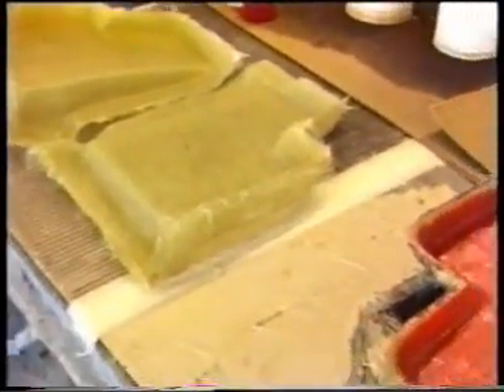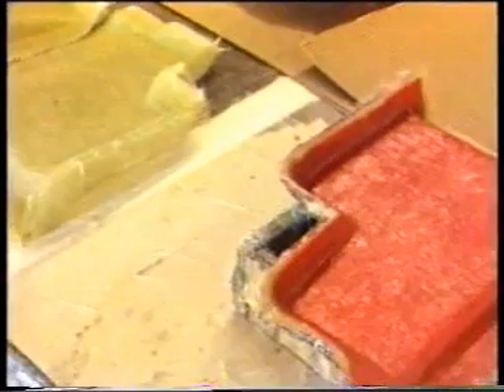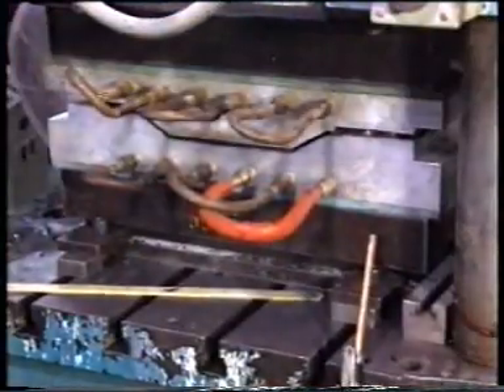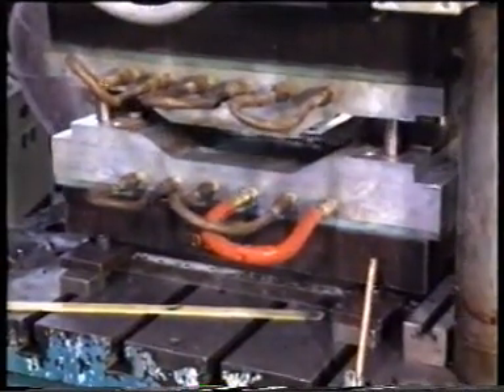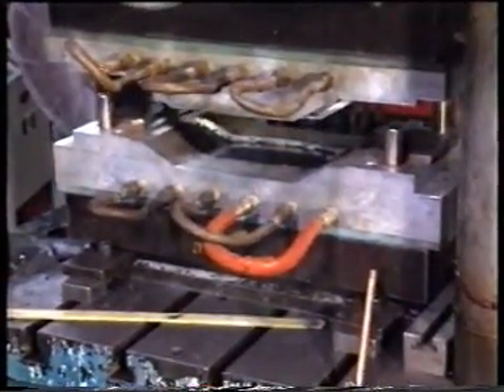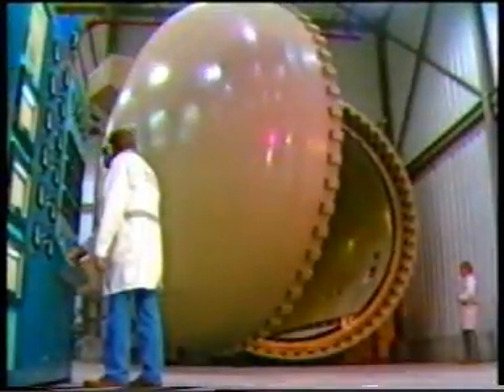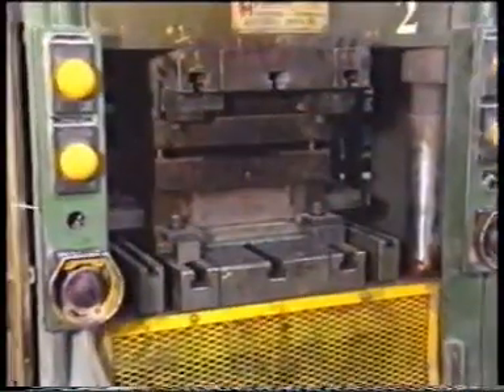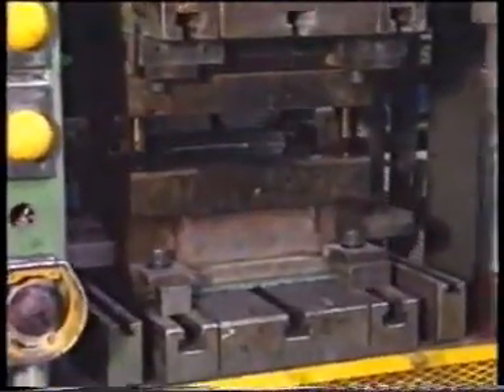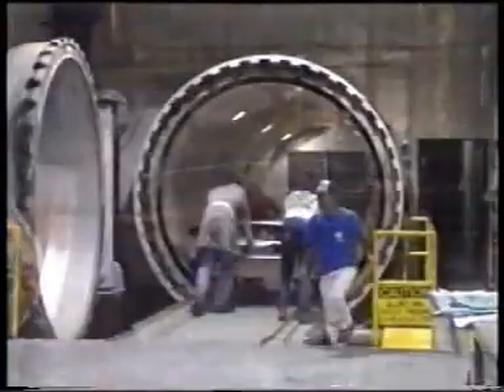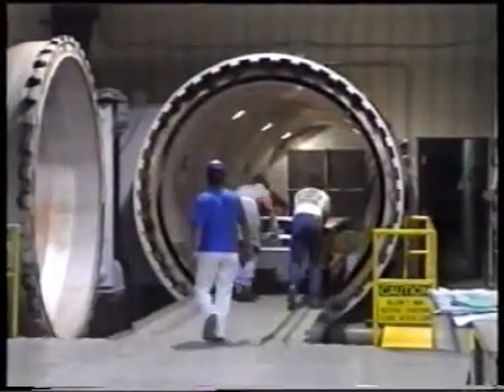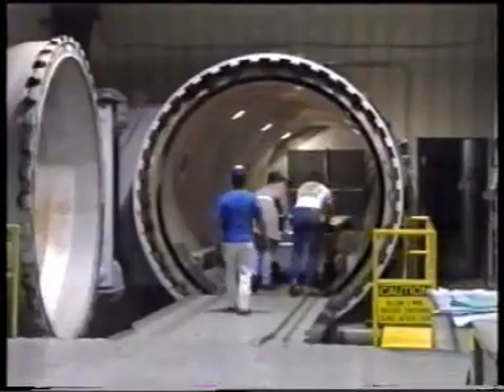After layup, composite parts may be allowed to cure at room temperature or with open-air heat assist. Composite parts are also commonly consolidated and cured in heat-platen presses, ovens, or autoclaves. Curing cycles for composites can be lengthy, ranging from an hour to half a day or longer. The process is typically faster in presses than in ovens or autoclaves, but ovens and autoclaves can accommodate much larger parts or many small ones.